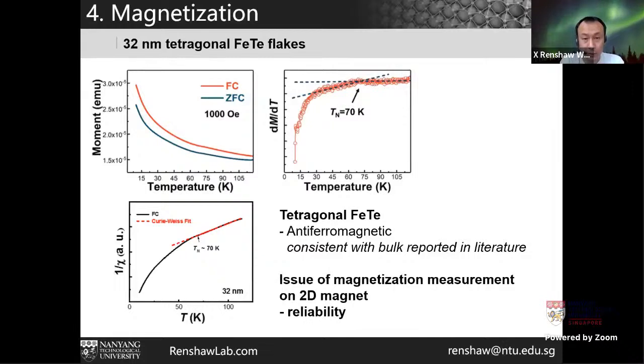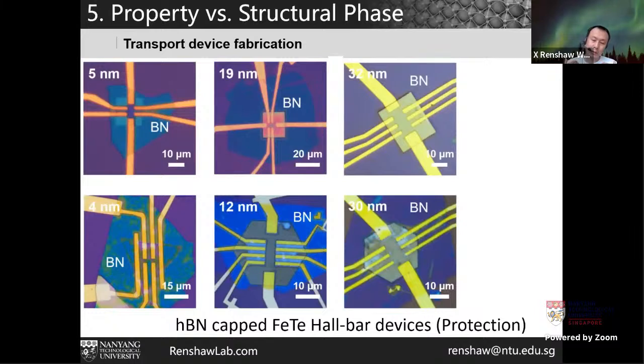So this is, in my opinion, an issue, and some material scientists are making mistakes. That's why I want to claim it is actually way more reliable to do the transport measurement to characterize the magnetic properties. It's kind of an indirect way to measure the magnetic properties, for example, measuring the anomalous Hall effect.